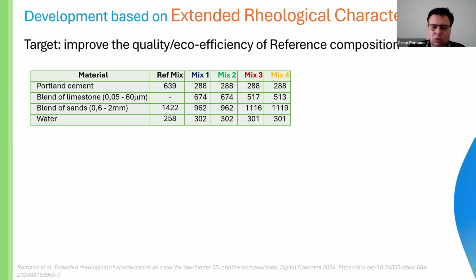This reference mixture consisted only of natural sand and cement. And you can see here, the Portland cement consumption was very high. Very high for the target that we have here, but not for the target that we have worldwide. So, although we immediately recognized that the cement content was above our sustainability targets, it was essential for our research to first characterize the rheological behavior of that composition that works in that machine.